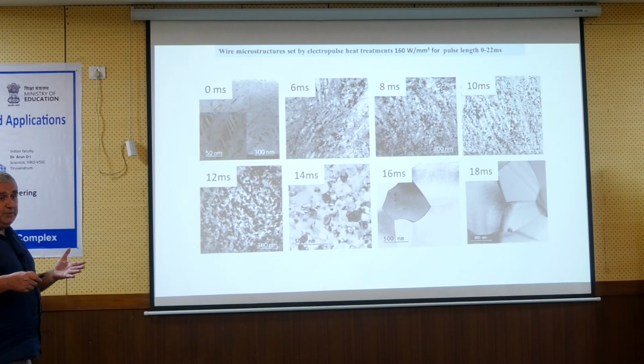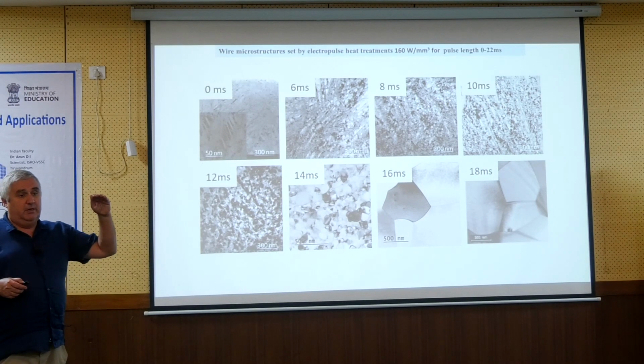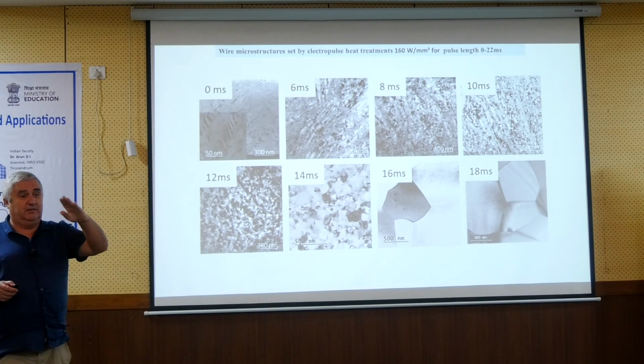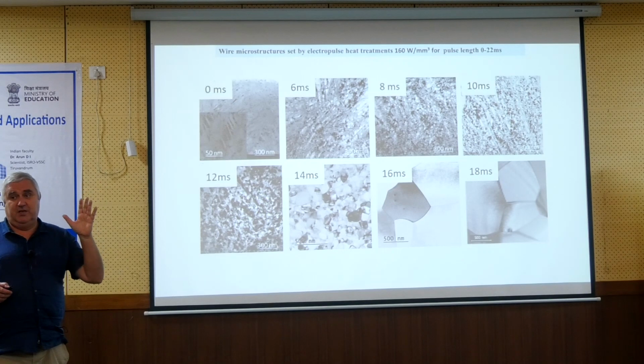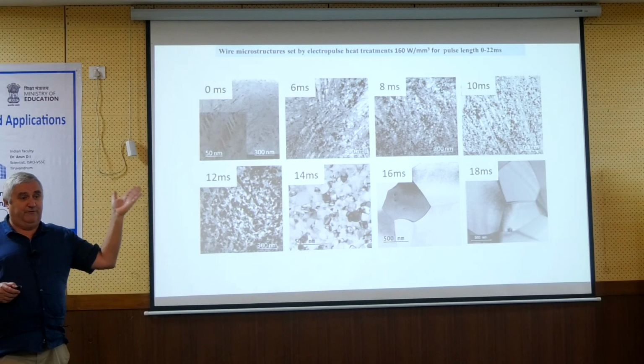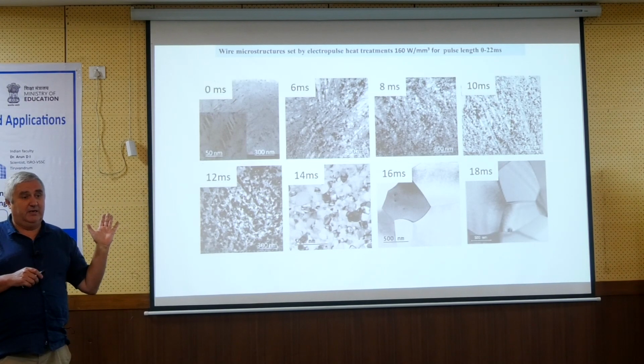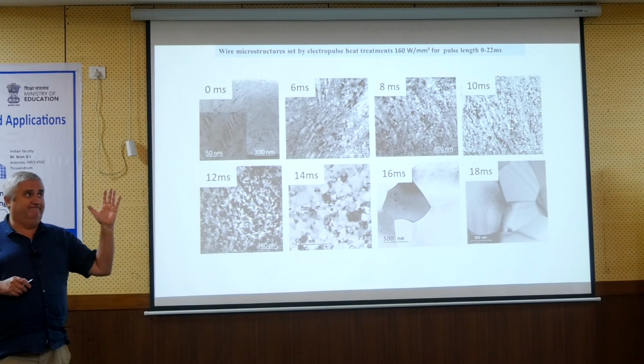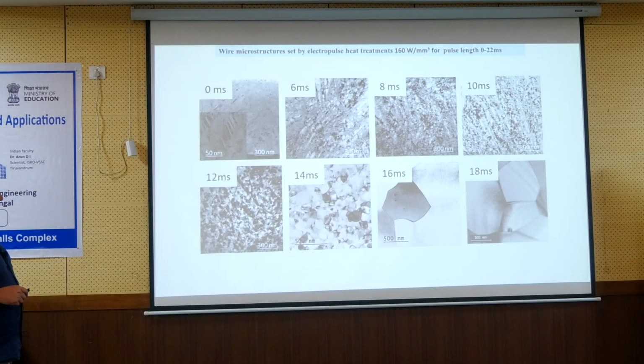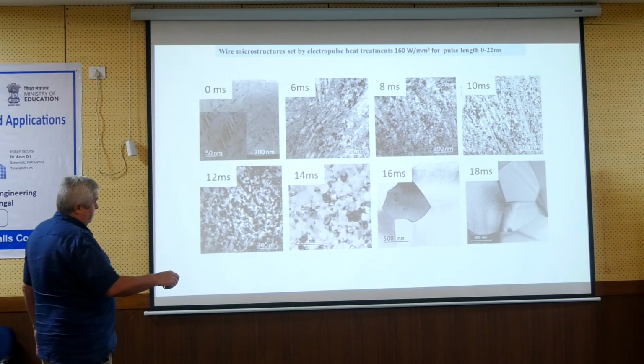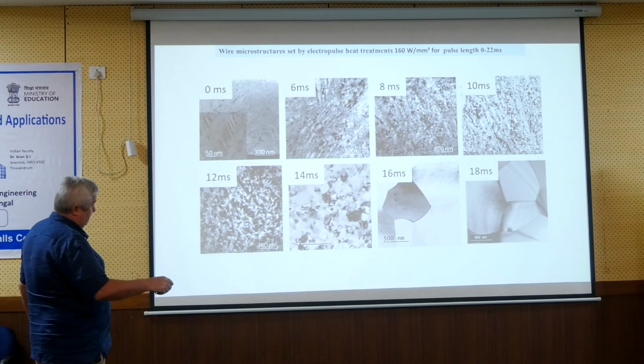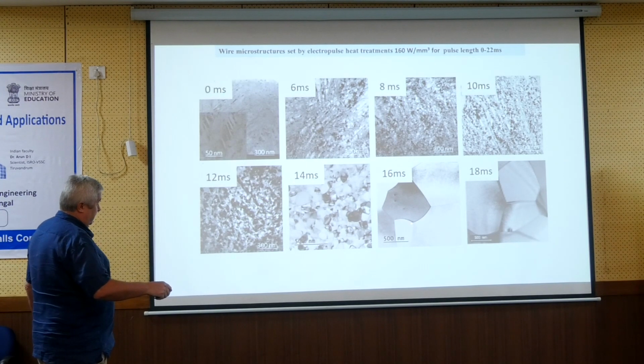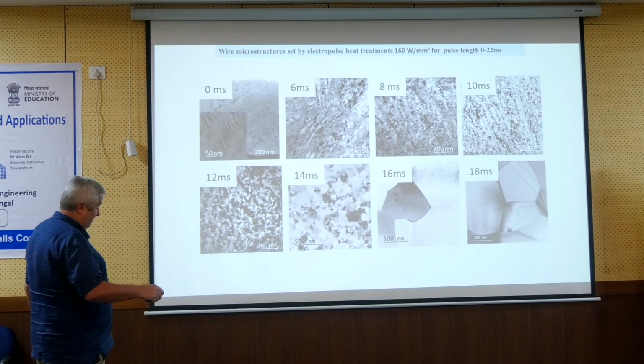Yeah, you will obtain something similar if you put them at 300, 400, 500, 600 temperatures into the furnace for something like 5 minutes. You know, not more. But there are some differences. For example, here, if you look into these grains, if you search for this location, you will hardly find one.